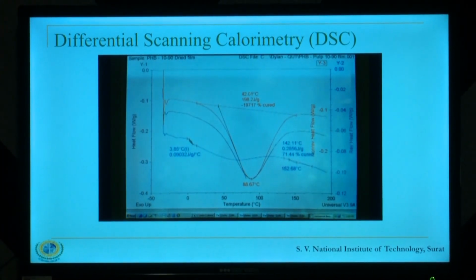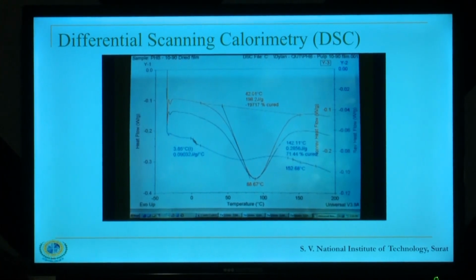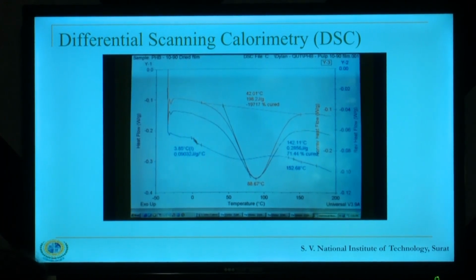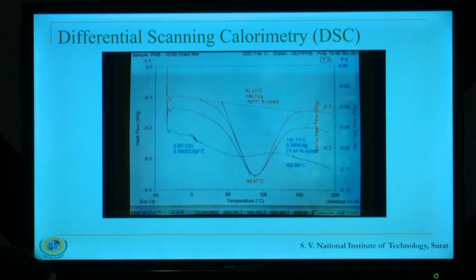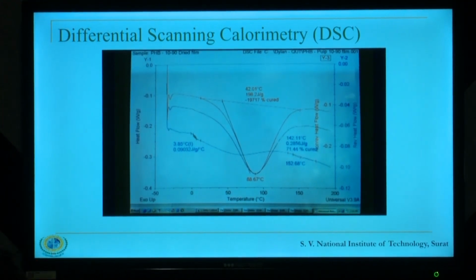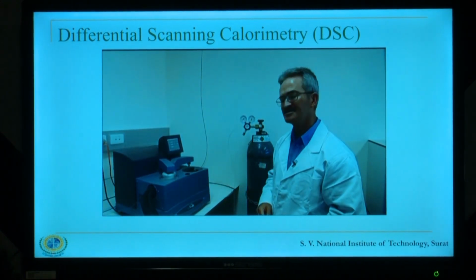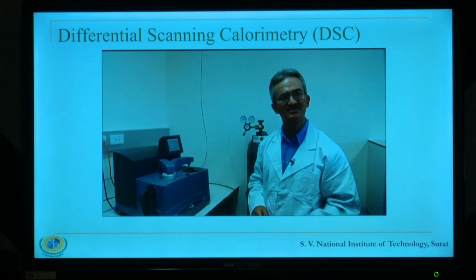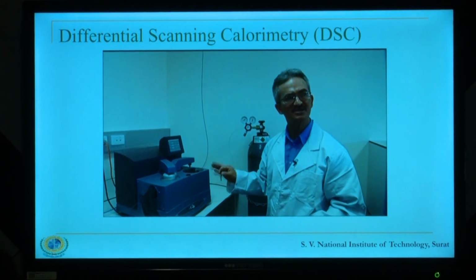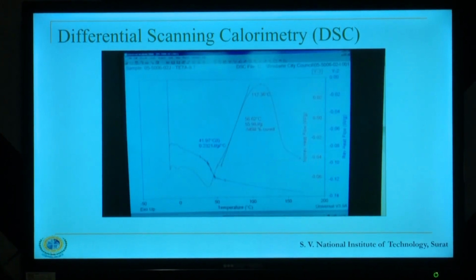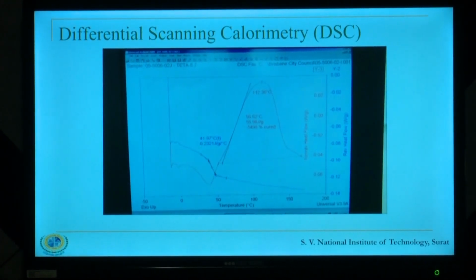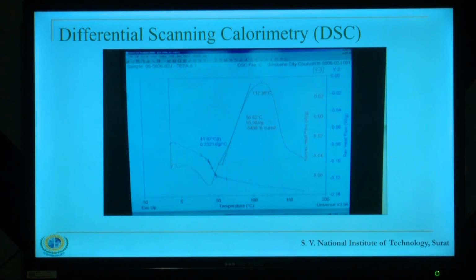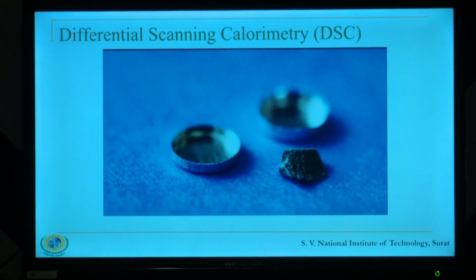Depending on the thermal properties of the sample you want to measure, you can set the software on the test you want: standard, for the determination of the total heat of reaction, or modulated DSC, also known as MDSC, for such properties as the Tg value, the melting temperature, and the degree of crystallinity. The DSC analysis is done under nitrogen gas to minimize oxidation reactions and obtain only the thermal properties associated with the polymeric material. The glass transition temperature, Tg, is the temperature at which an amorphous solid becomes brittle on cooling or soft on heating. The degree of curing determines the amount of the sample, percentage weight, that is cured or polymerized. The degree of crystallinity is the amount of the polymer that is amorphous and the amount that is crystalline, percentage by weight.